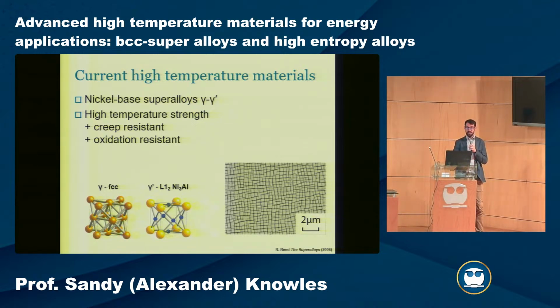So you have this FCC matrix, which gives you ductility, and you reinforce it by this nickel-3 aluminium intermetallic that has the high temperature strength, but probably lower ductility. So you can tie the two together, the high strength of the intermetallic and the toughness of the FCC matrix. So you can get this brick and mortar style microstructure where the cubes are actually the gamma prime, and then the channels in between them, which is the matrix, is the gamma.